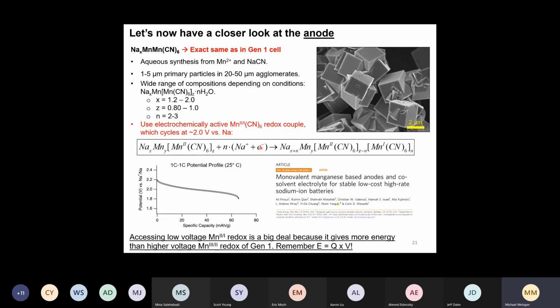And electrons flow in the external circuit. And then in order to compensate for this charge that you put in the structure, the manganese, which is initially in the 2+ state, which is bound to the carbon atoms, reduces its oxidation state to manganese 1 CN6. So you end up with a mix of manganese that is still remaining in the 2+ oxidation state, and some manganese, in fact, N worth of manganese, which changes its oxidation state to 1.